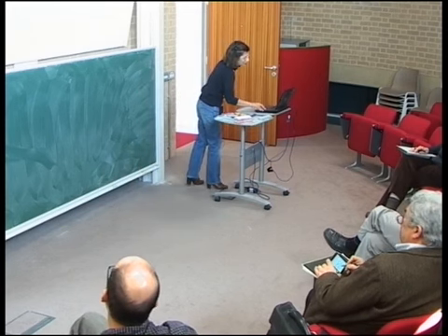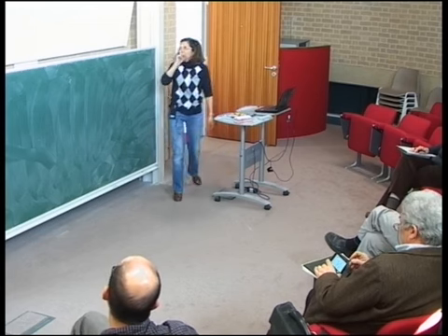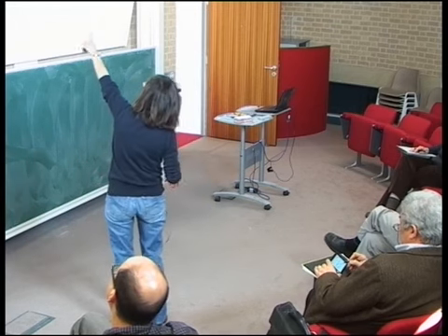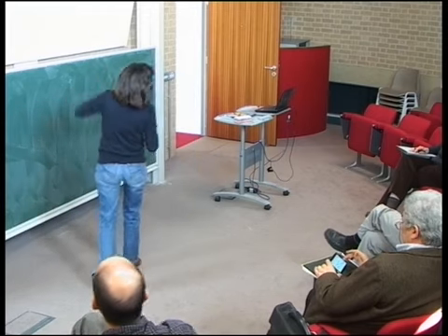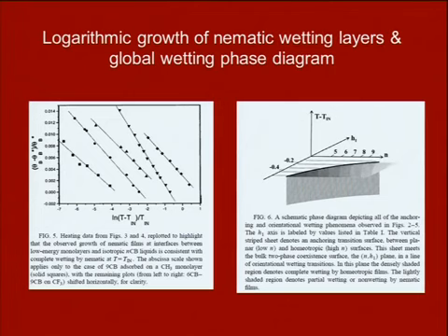It's sort of local almost, but they did try two things which are relevant. One I'm not going to discuss. They actually measured how the nematic order grows with the temperature, and they found a log. This is the celebrated short-range result, which in simple fluids you don't see because there are always dispersion forces. And well, we can maybe not discuss why they find that.